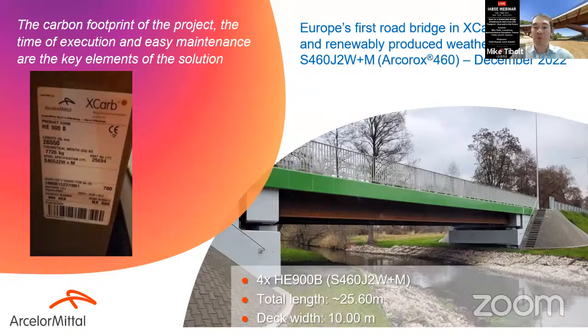Why was it important to have these choices? First of all, the investor would like to have an easy and not so heavy solution. That's why he went for a composite bridge with hot rolled sections. And by using a weathering steel, there was no need to put a painting on the bridge, because for weathering steel, we have this auto protection, this patina, which will form automatically and ensure the corrosion protection. And so we do not need to redo the painting over the lifetime of the bridge. So also the maintenance efforts will be reduced. And of course, we have no detrimental negative impact on the environment coming from the painting.